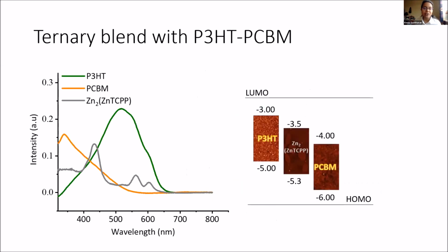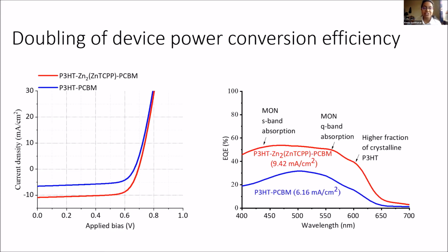So harnessing these benefits of MONs, these porphyrin MONs were then investigated in a ternary system with P3HT-PCBM, mainly motivated by the ideal position of their band gap with the donor and acceptor in the system. After optimization, we found that about 20% by weight of these MONs in the ternary system contributes to a near doubling of device power conversion efficiency with simultaneous improvement in JSC, VOC, and FF. A careful look at the EQE spectra shows that there's enhanced absorption from the contribution of the porphyrin groups in the MONs system, and also a higher percentage of crystalline P3HT in the system.